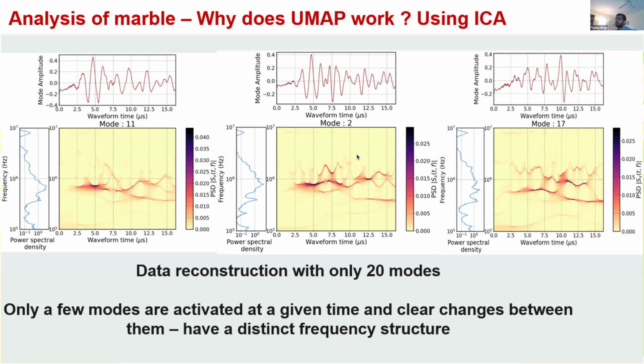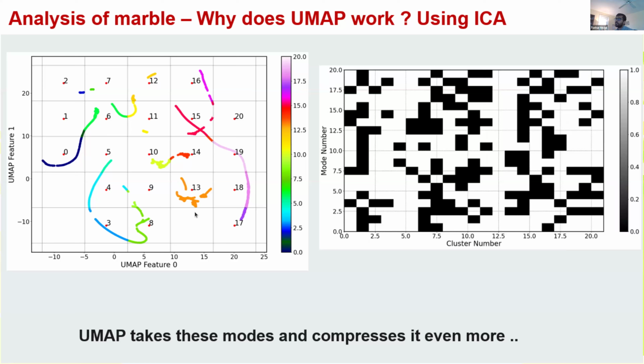the spectrogram. As we go from mode 11, which is dominating the low frequency, lower pressure experiments, to mode 2 and 17 that are dominating the high pressure experiments, the more ductile behavior, we start to see subtle changes in the frequency, a little bit more high frequency content coming in, but also the structure of those is different in time domain. So using this and doing a bunch of back processing that I'm happy to talk to people about offline or later after the rest of the seminar, we can figure out basically in the parameter space what UMAP is actually picking out in the context of the modes.